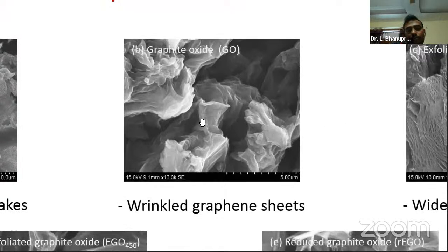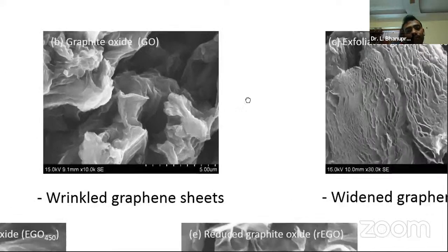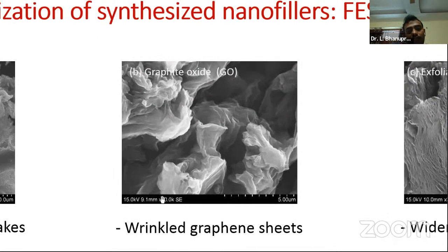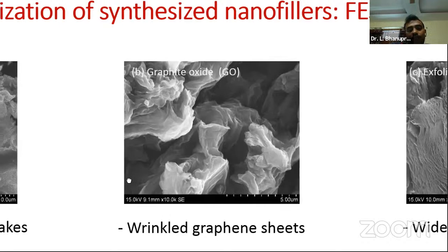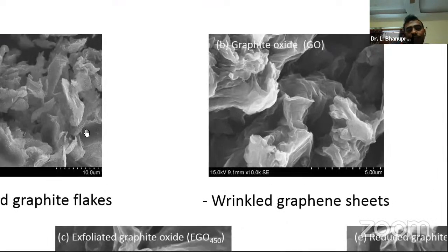So this is an SEM image of the graphite oxide. You can clearly see the stacking is being reduced. I mean, the size of the graphene is being reduced here, and so the magnification also. We have to go deeper to analyze the component. That is 10K magnification, whereas here it is 30K magnification.